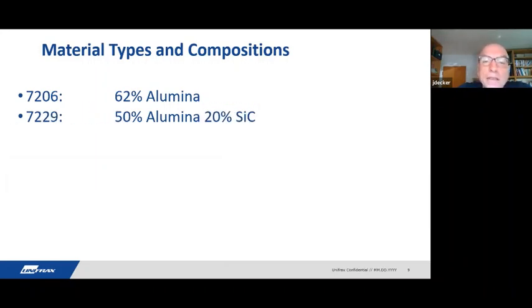Material types and compositions. So over the years, we've developed quite a few materials here. The workhorse is a 7206. It's a 62% alumina material with high mullite content. 7229 is basically the same material, but with 20% silicon carbide. This works well in cement application because the silicon carbide content makes it very corrosion resistant against potassium vapor, sodium vapor attack. It also works well in applications where you have low angle abrasion, like in sills and ramps in the aluminum industry, floors, and it's non-wetting because of its silicon carbide content.